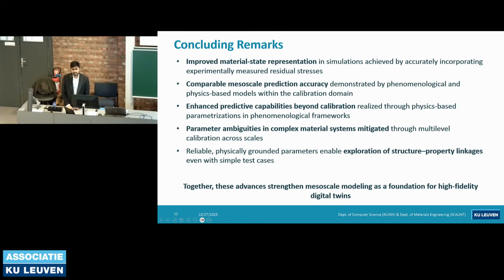And how much would it improve? What I actually want to know is how important it is to have your initial microstructure exact. This is quite important in my opinion, because if you want to predict fatigue life, especially high cycle fatigue, the models that we currently use only use the data from the first few simulations, the first few cycles, and then extrapolate this. As we saw here, residual stresses significantly impact the behavior in the elasticity-dominated regime. If in the first few cycles the stress values are quite off, then the fatigue life will be impacted significantly. So for fatigue, it would be very important to have even the smallest details such as residual stresses incorporated correctly in the entire volume. Okay. And it will also impact the yielding of certain grains. Thank you.